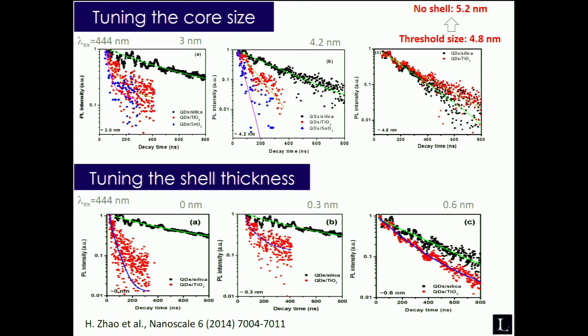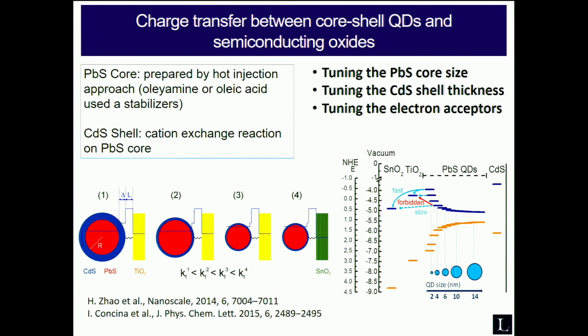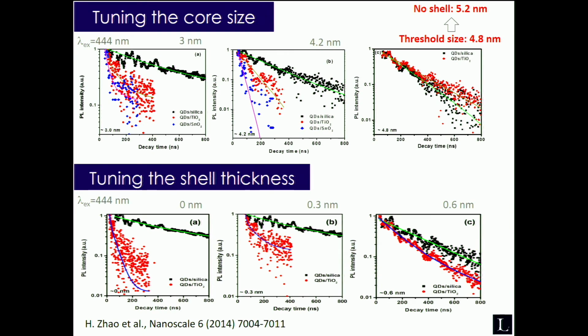As you can see here, injection to titanium oxide, which is the red dots, has a longer lifetime compared to tin oxide, as we expect. Because this is titanium oxide, this is tin oxide, so I expect a much faster and favored injection into tin oxide, and we proved it.